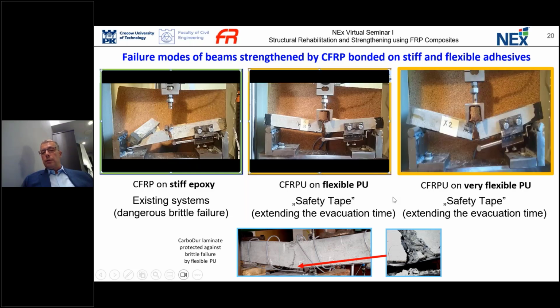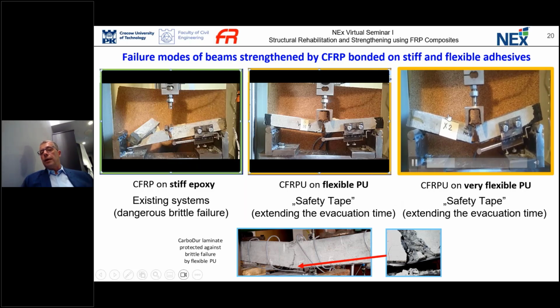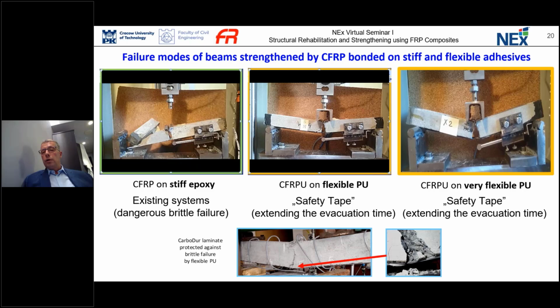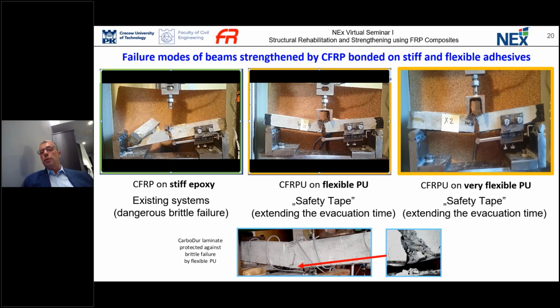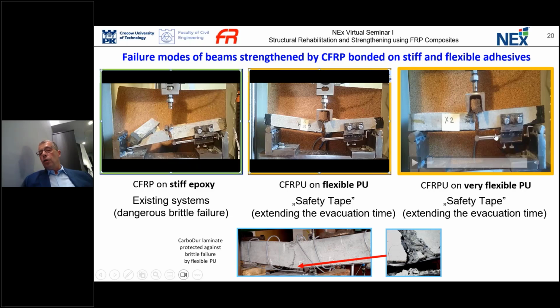If we use the very flexible material, you can clearly see that the deflection is very warning. So in this case, people can escape from such a structure, or in an emergency, teams can also rescue people. But what is very interesting, after unloading, the structure moved back to the previous position. So in this case, we give time for evacuation, and we also give authorities time to make a decision on how to manage such a structure.